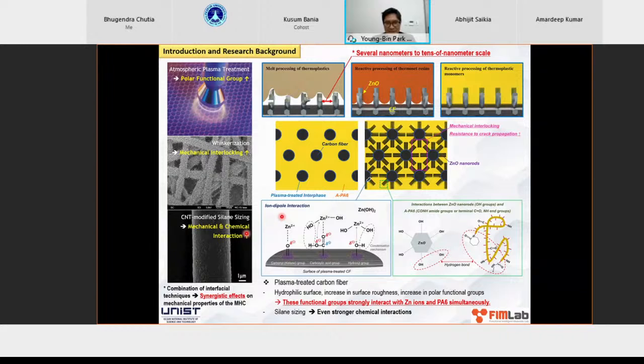Okay, so I just explained two approaches: number one, plasma treatment, and number two, sizing. And number three goes back to my previous slide, when I showed you reinforcing the interfacial region between the fiber and the matrix. Almost every fiber is treated with a coupling agent, and oftentimes silane is one of the most common types. In this case, our intention was to mechanically reinforce the silane coupling agent by adding carbon nanotubes. So in the third approach, we added carbon nanotubes to silane, which was eventually coated on the surface of carbon fibers. I'm going to explain this in a more graphical way.